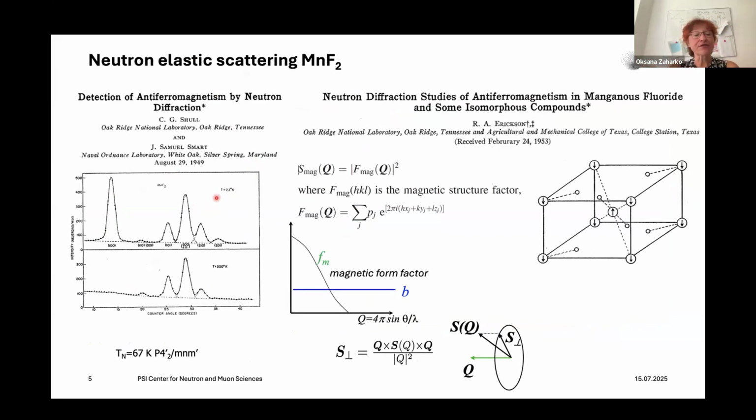Even all this is averaged. You have just the lengths of Q, and from such measurement, especially where Q is quite small, you can have a rough structure. So this dipole approach, having antiferromagnetic moments, is completely correct. Now, if you want to dig further, you probably should go to polarized neutrons.